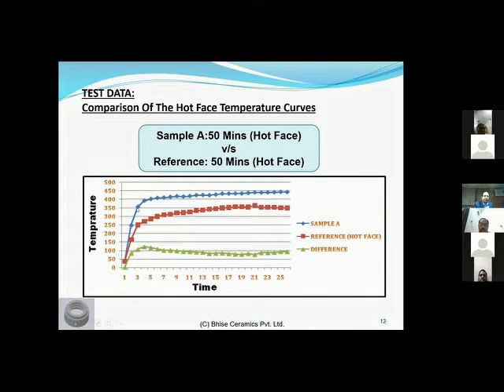If you see this ramp up curve, though it's similar, you will see it is far faster and far steeper, which indicates that when you have a barrier to the heat, the entire heat is getting concentrated on heating the base plate, and a very little amount is getting transferred. So you have a very fast ramp up.